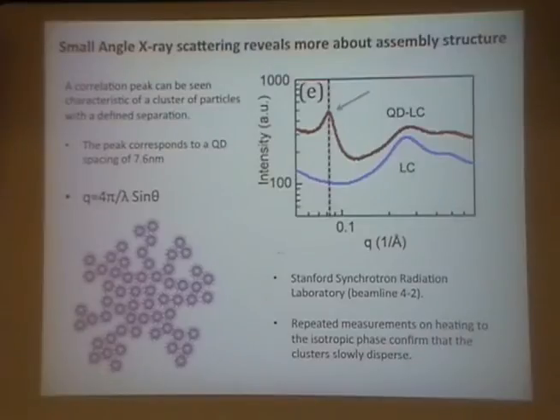When we do the same sample with quantum dots, with the clusters, now we can see a new peak forming. If the quantum dots were just dispersed, we would not see any peak, because they would be diluted and randomly arranged within the liquid crystal. But because we have clusters, we see a peak here, and this peak tells us the average distance between neighboring quantum dots. So it's telling us that within the cluster is a characteristic length scale of ordering. I have a little diagram here to represent it. We think the ligands really set the spacing. They give a characteristic distance. We measure from this peak 7.6 nanometers between quantum dots. Quantum dots are about 5 nanometers in size, plus ligand, so we definitely have some interdigitation of those ligands.